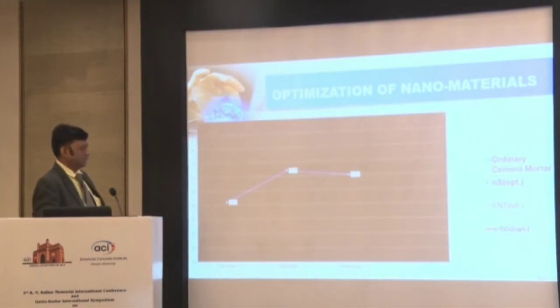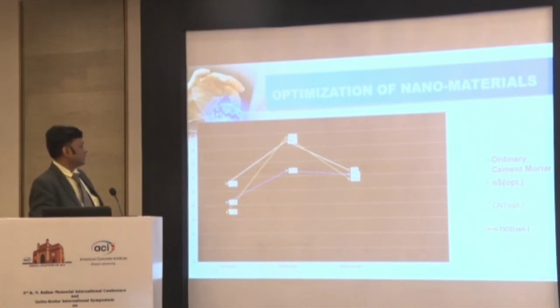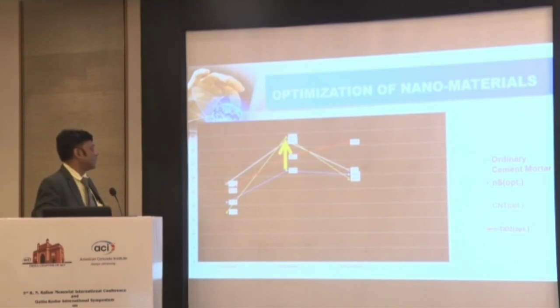This is my control sample. This is my nanosilica addition. This is my carbon nanotube addition. And this is my nanotitanium dioxide addition. See the increase in strength from the control sample or reference sample. The carbon nanotube sample shows the maximum increase. So we are saying this is optimized.